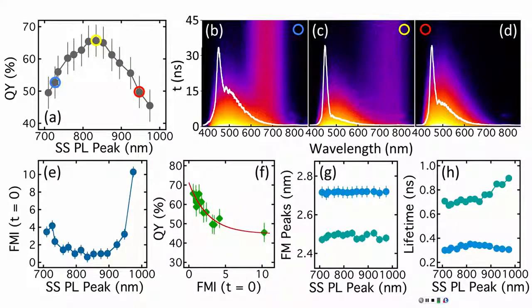So you're telling us that in this intermediate range between truly small nanoparticles and bulk, there is a violation of momentum conservation. There are optical transitions with change of momentum. Your emission from the main band, which you call bulk, and indirect, right?